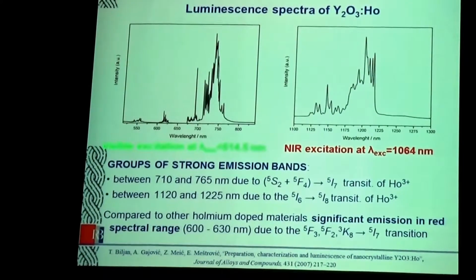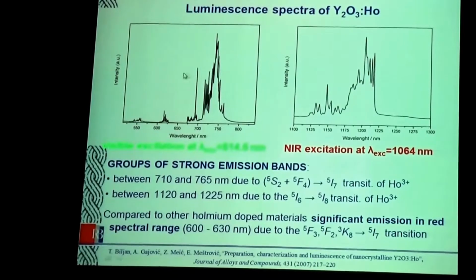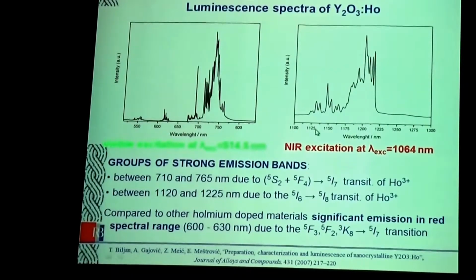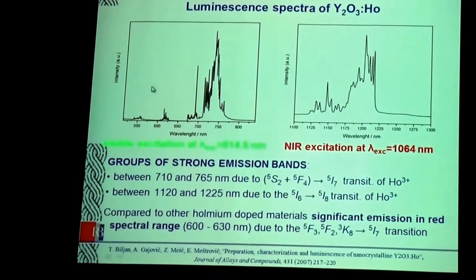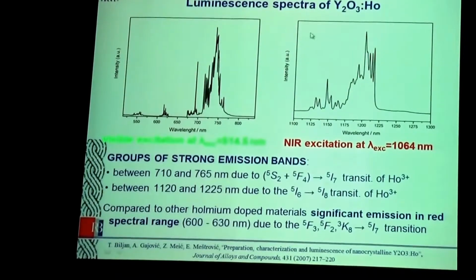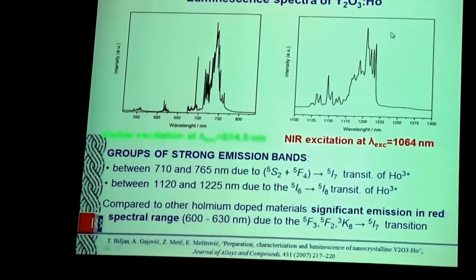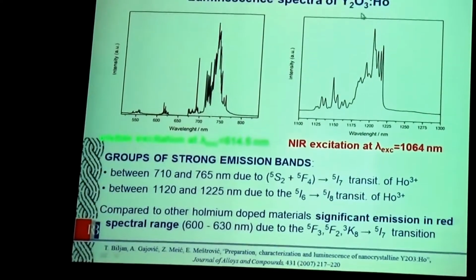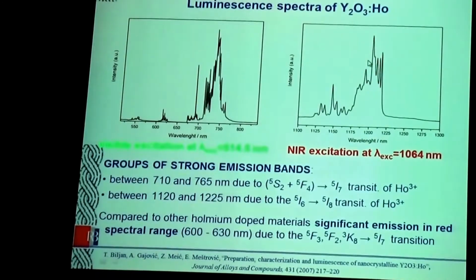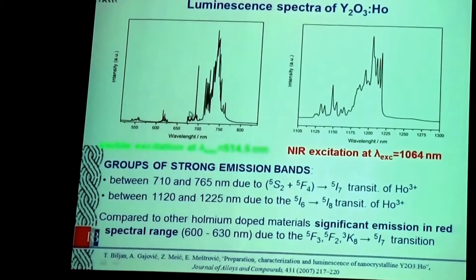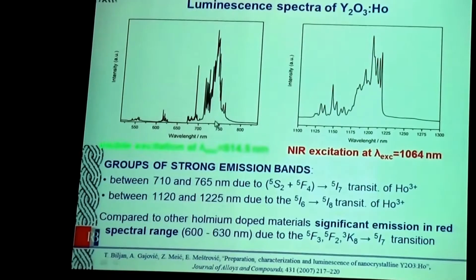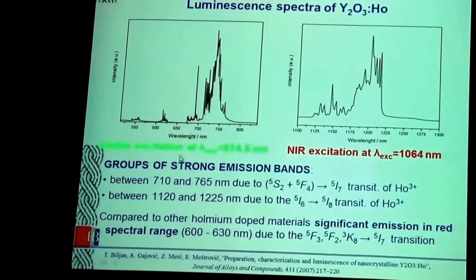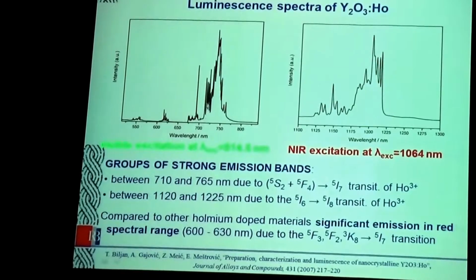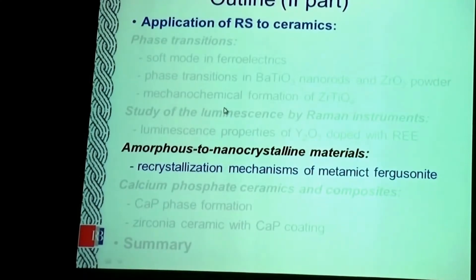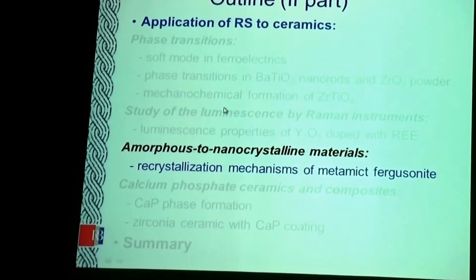Due to this reason, we used our instrument. This was a collaboration with one colleague who had a Fourier transform Raman. So we made a whole study of the luminescence spectra in a system like yttrium oxide doped with holmium. Later on we used different rare earths. This study is also important since we can easily resolve this band. Normally with a UV spectrometer you cannot resolve this f orbital transition so nicely.